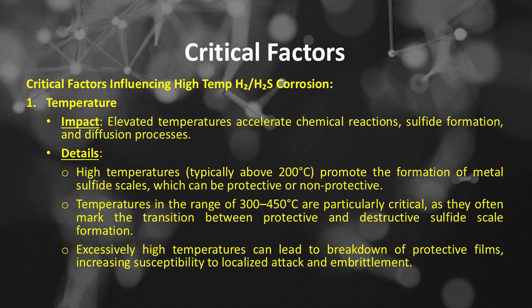Critical factors influencing high-temperature hydrogen or H2 and hydrogen sulfide or H₂S corrosion include, number 1 is temperature, the temperature impact. Elevated temperatures accelerate chemical reactions, sulfide formation, and diffusion processes. For details, high temperatures typically above 200 degrees Celsius promote the formation of metal sulfide scales, which can be protective or non-protective. Temperatures in the range of 300 to 450 degrees Celsius are particularly critical, as they often mark the transition between protective and destructive sulfide scale formation. Excessively high temperatures can lead to breakdown of protective films, increasing susceptibility to localized attack and embrittlement.